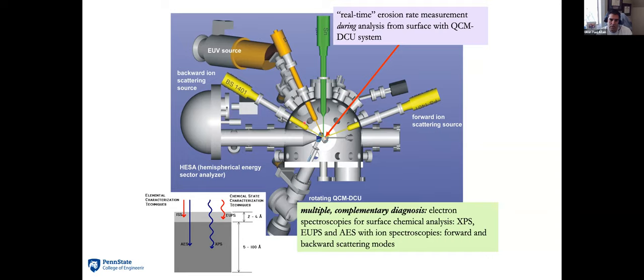And in addition, in the system, in addition to the ion sources which we call the probes, which run about two orders of magnitude lower flux than the modifying sources, what you're seeing here are the modification sources. These are sources that are trying to modify the material surface in some way.